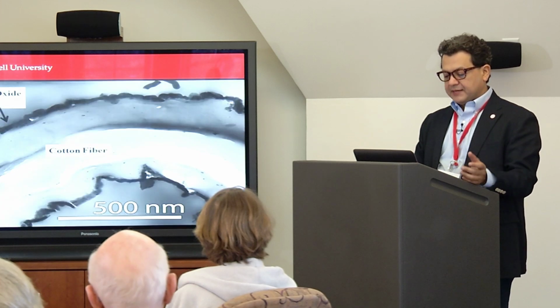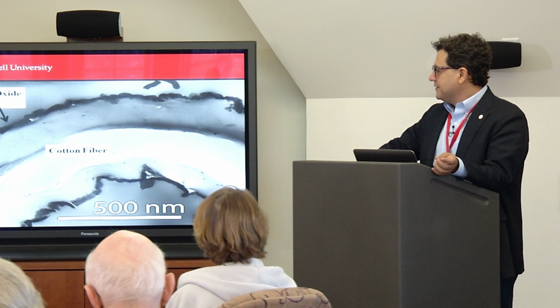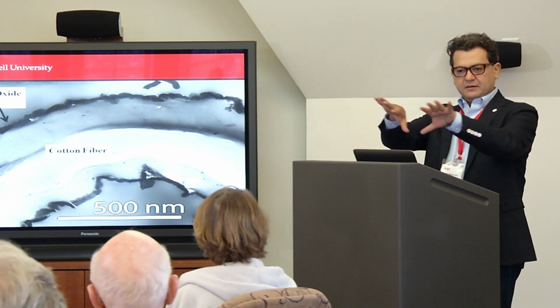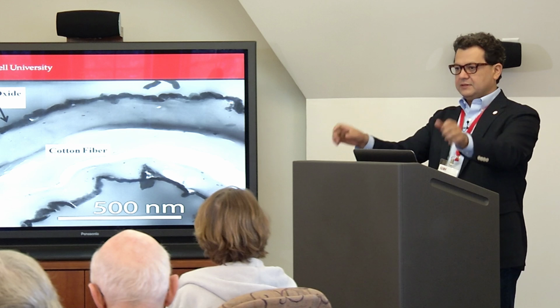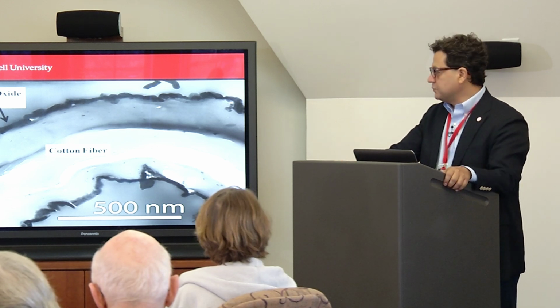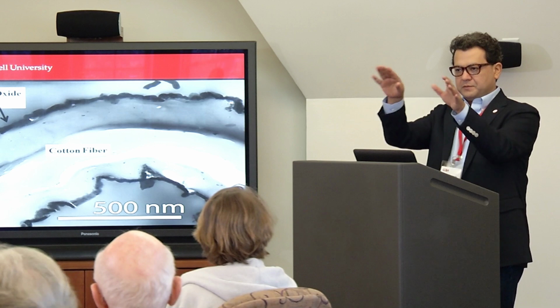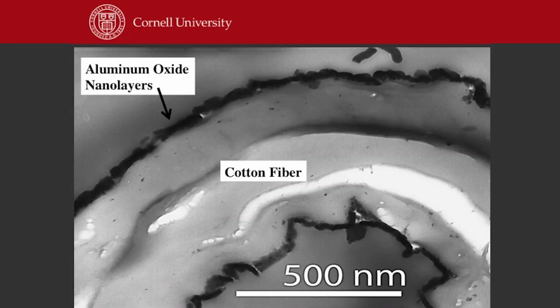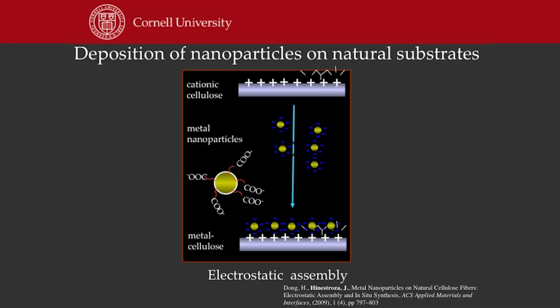And then I decided that perhaps these layers, as beautiful as they are, may break because they are layers on the surface. So when you bend them, they will break. So we decided to move to objects that will be able to conform to the surface when they bend. So we use nanoparticles. So instead of a single layer, we work with individual particles. And we have the same process. We have very small particles. We put them negatively charged. They assemble on the cotton and then create a layer, but the layer is composed of small particles.